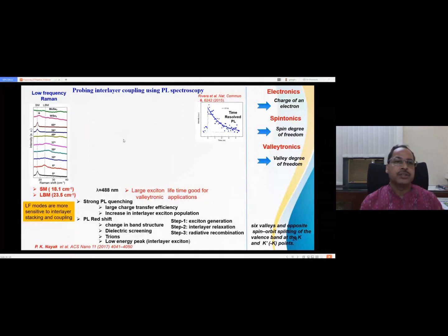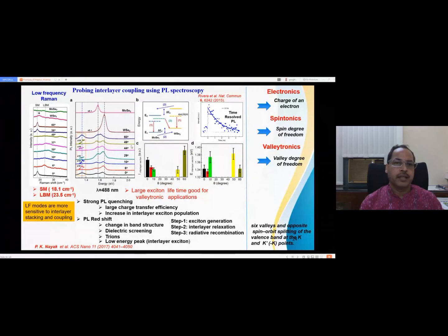There are many papers in ACS Nano about the low frequency modes of this twisted bilayer after 2016-17. Then we have done the PL measurement. Here you can see the PL. This is the typical one layer, and this is the other one layer WSe2. When you make the heterostructure, you can see there is a sharp decrease, one order of decrease in magnitude, and there is a PL shift also. This is the first observation: there is the PL quench, there is a PL shift. Quench you can explain because some of the electron-hole pairs generated go into interlayer recombination. That's why there is a quench.